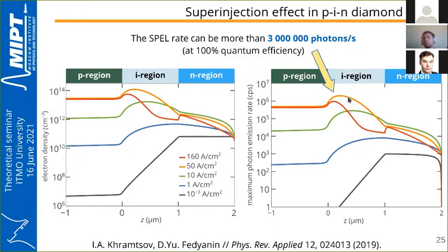You can see that the results are counterintuitive, because the high electron density appears near the PI interface and not near the NI interface.